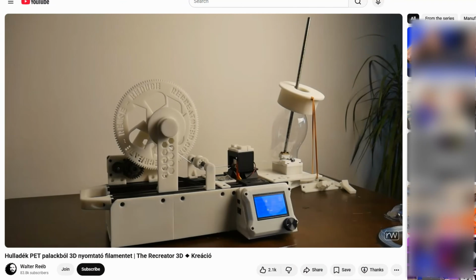Our first thought may be that this recycled PET is quite weak, but it's not. I already saw other videos too, and the main reason for this weakness is actually the underextrusion, which I mentioned several times, which is a result of this dimensional inaccuracy. And this shows the weakest point of this Recreator 3D, that we put in a lot of work and then we get 8 meters of sample filament, and maybe we don't even know that it is dimensionally inaccurate, and we print some mechanical parts and they will be weaker.